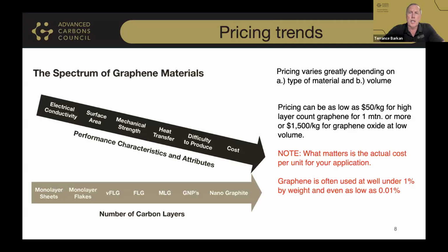I would say that the pricing for graphene is extremely volume dependent. So there's a huge difference between buying a gram, a kilo, or a ton of the material. But the real important aspect to understand, in almost every case, graphene is not used by itself. It's used as an additive for another component. And this is especially true in the case of composites, where graphene might be in the resin system and is used at a fraction of a percent.